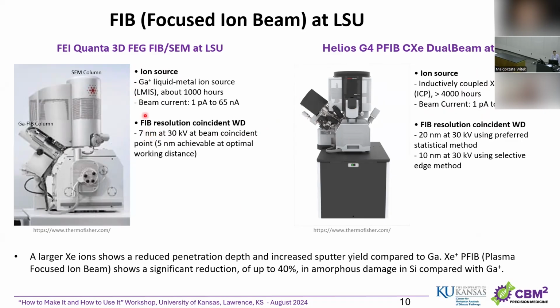But what you can see here is for gallium ion FIB, the smallest structure you can produce is around 7 nanometers. So this is the smallest beam size you can produce using this gallium-based FIB. While for xenon-based FIB, the smallest beam size is around 20 nanometers. So you can just imagine, okay, with this xenon-based FIB, you cannot really make small structures. However, you can mill very fast. I will just show shortly.